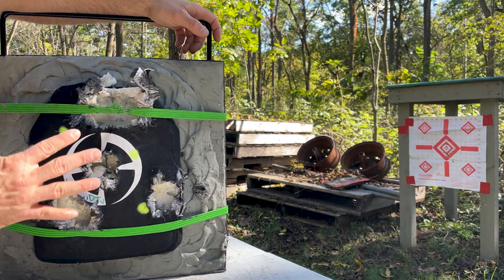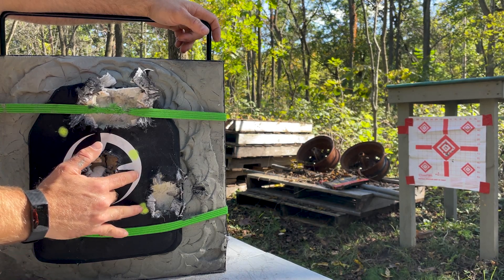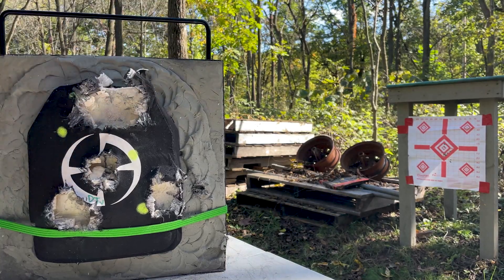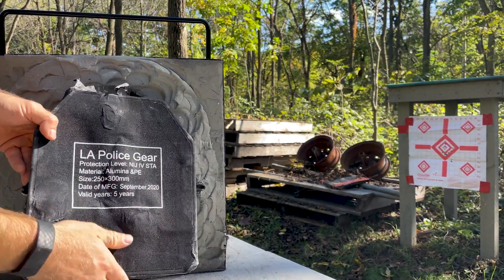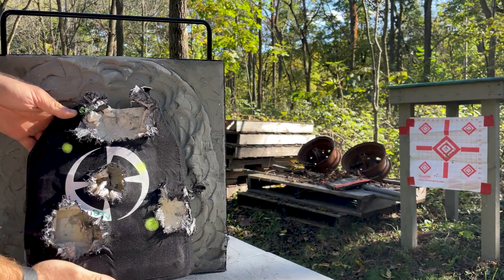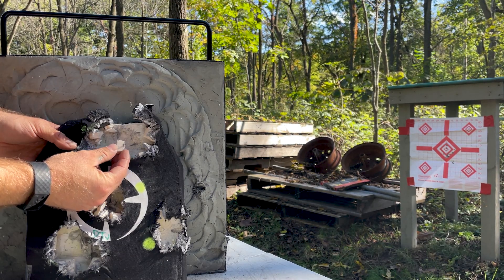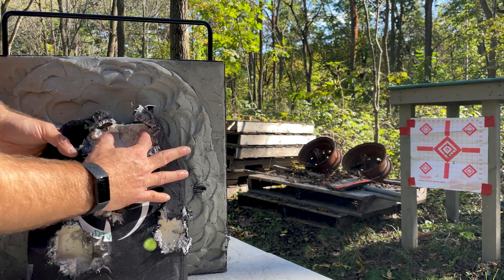At least one successful part of this test: I got all four shots on the plate and would consider all of them fair hits. The NIJ testing allows a minimum of two inches between hits, and these are well over that — sometimes they use even three. Shot number one, two, three, and four — that destroyed one of my straps already. No pass-through at all, and the dimples on those impacts are nothing to write home about with level four. A 55 grain pointed soft point going 3,800 feet per second is no match for an alumina tile array plate. These tiles are pretty thick — about 420 thousandths total thickness. Alumina is really good at stopping a lot of threats, though the plate is falling apart with some big chunks taken out.